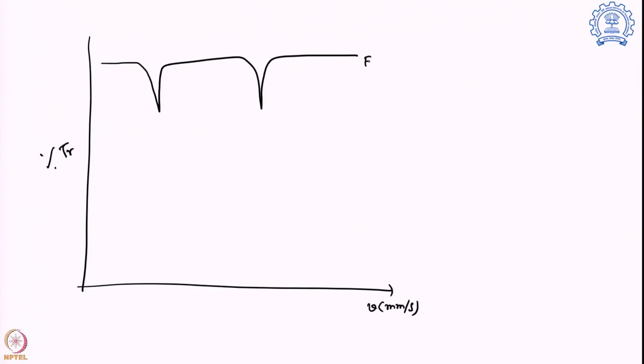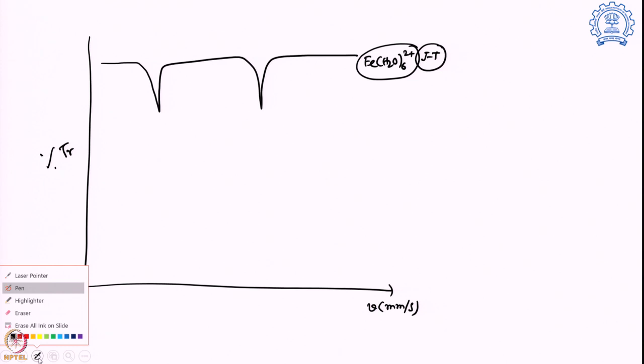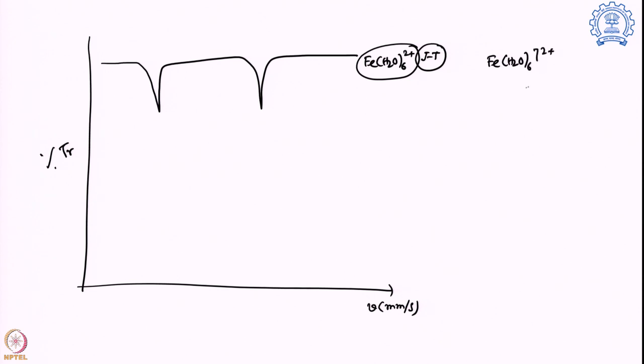So this is the iron H2O 6 2+ solution with Jahn-Teller distorted geometry, and I am seeing this particular system. Now what I am going to show, I will try to put the original data in black and the newly appearing system in the beginning. So in this particular system, we actually hit gamma rays. This gamma ray is a little bit different in energy than the gamma ray we are using for Mössbauer spectroscopy, but it is still high enough in energy that it can trigger some reaction in this chemistry.